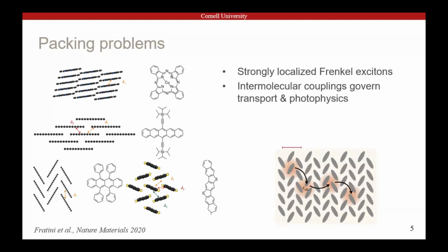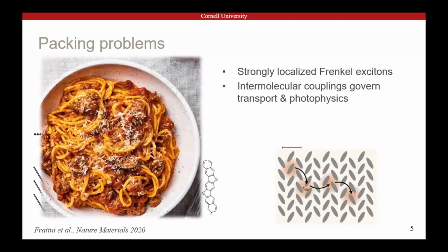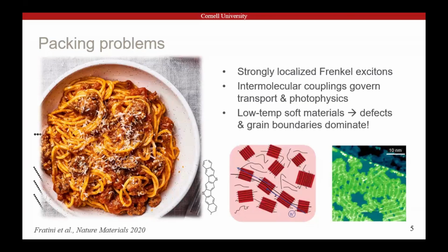But while this works really nicely on a sheet of paper and in your leading studies where they demonstrate this single crystal has very good transport, if you want to make an organic semiconductor device using the advantages of solution processability, it's never going to look like this. A real organic film looks much more like this. You get this horrible mess of different domains. You might have some of these well-defined crystalline domains inside where you know the packing, but they're swimming in a sea of amorphous material, maybe connected by some semi-crystalline regions.